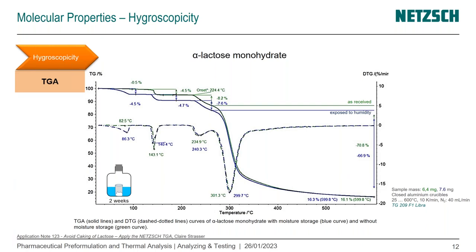In contrast, when we have amorphous lactose, it is very hygroscopic. At a certain humidity, amorphous lactose is transformed into crystalline alpha-lactose monohydrate form that exhibits change in its compression properties. This sample here contains about 10% of amorphous lactose.